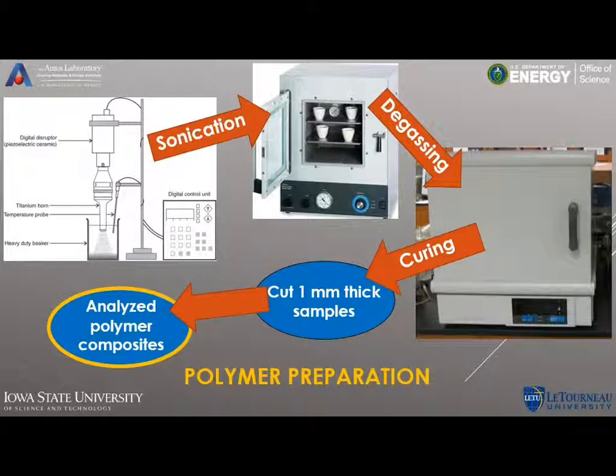And because of those gases that we saw in the material, as a second step, we went on to degassing in a vacuum oven. And so we basically placed the liquids in this vacuum oven and just evacuated the chamber without heating it to allow that gas to escape from the liquid.